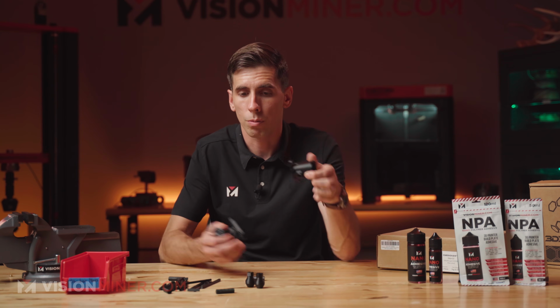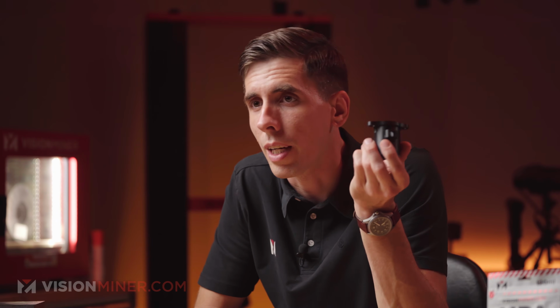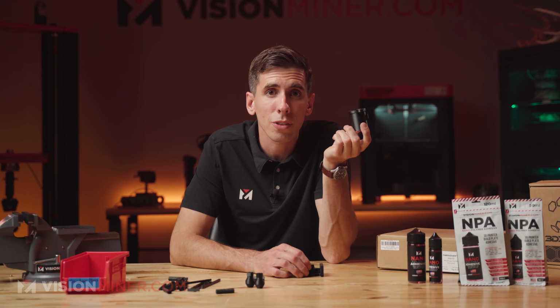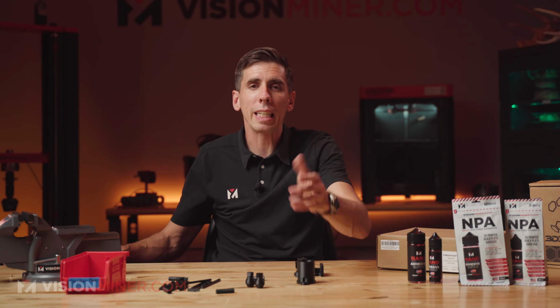If you can, use a vacuum oven or at least a vacuum chamber, especially with nylon, it absorbs a lot of moisture. So if you can get that vacuum chamber going in there, it really helps reduce the boiling point of the moisture and release it into the atmosphere at that vacuum. And if you do skip drying, you will definitely regret it. The material absorbs moisture very fast, and wet nylon prints are brittle and stringy and weak, and you just want to avoid it.